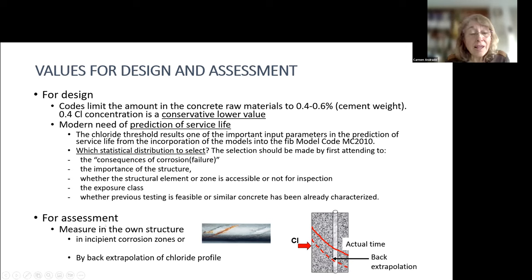And for the assessment, I would rather prefer the method that will be explained by Gro Markeset, because we have a RILEM recommendation, she will explain, or by back extrapolation. I don't like to take cores and retest in the lab for the chloride threshold, because you are changing the condition of the temperature and the condition of the core. And if you have this profile, you can try to back extrapolation to a lower time and to know what has been the chloride threshold when starting the corrosion.